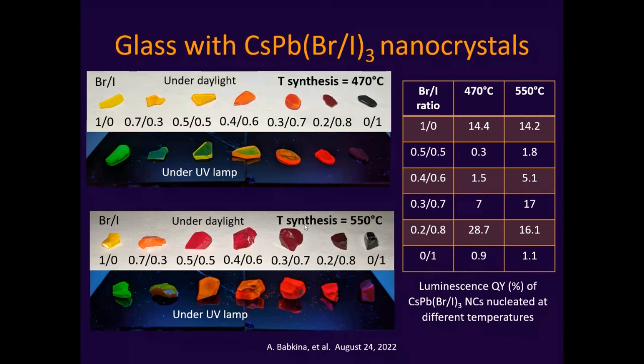As you can see, at daylight and under a UV lamp, they have different colors of luminescence. And by combining bromide and iodine ions inside of the composition of the nanocrystals, it perhaps can help us to tune the luminescence from the beginning of the green region of the spectrum up to the end of the red region of the spectrum. So we will cover like 2 out of 3 parts of the visible region.